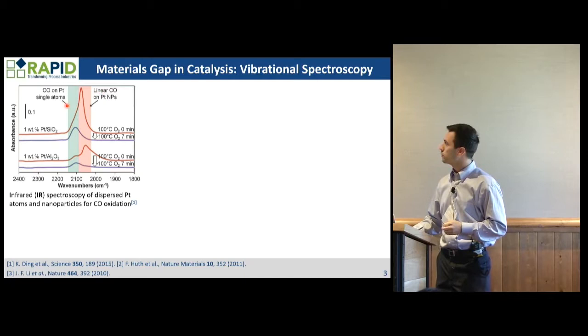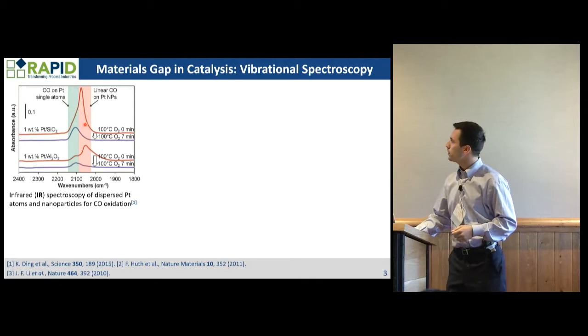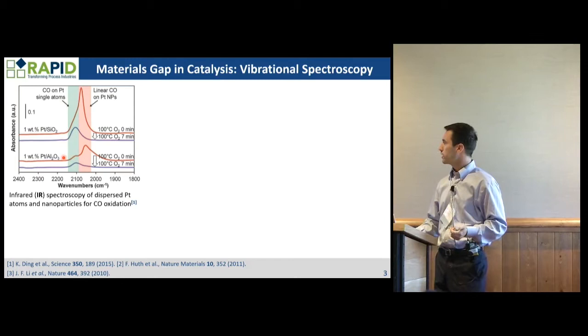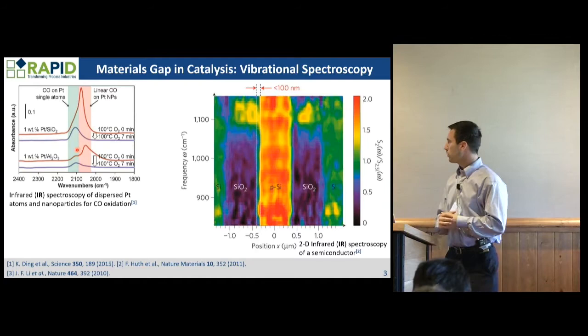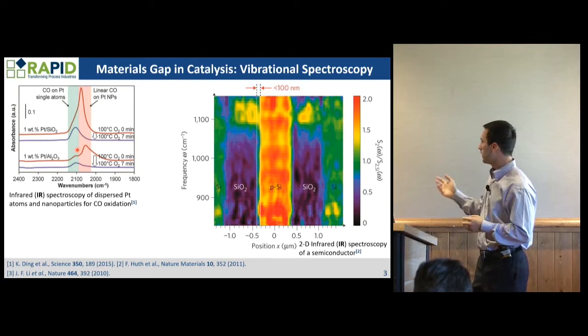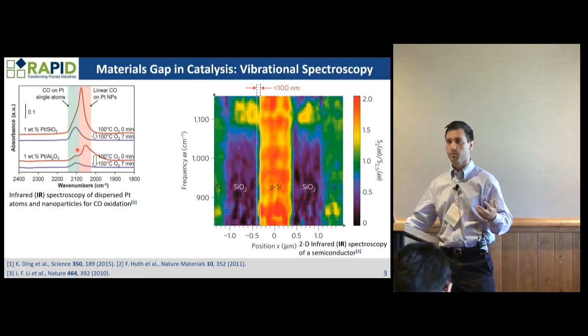There are both 111 facets, extended surfaces, as well as platinum nanoparticles. You can see how the concentration of the nanoparticles, given by the weight percent, corresponds to differences in the spectra. IR spectra also has very high spatial resolution — you can get micrometer and actually nanometer spatial resolution — and also has very high time resolution and can be used operando, which means it can be done during operating conditions, which is important.